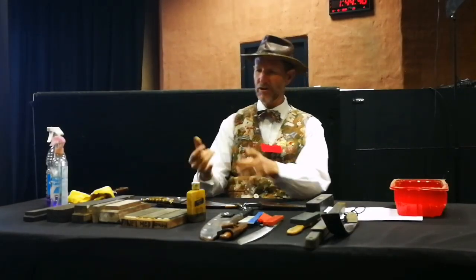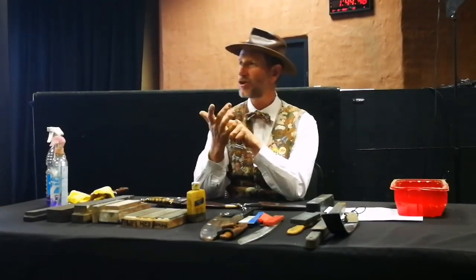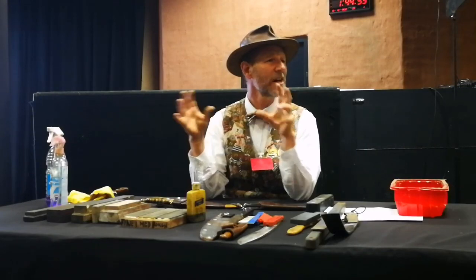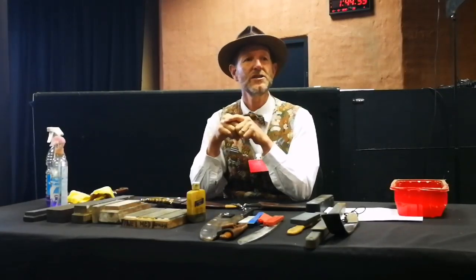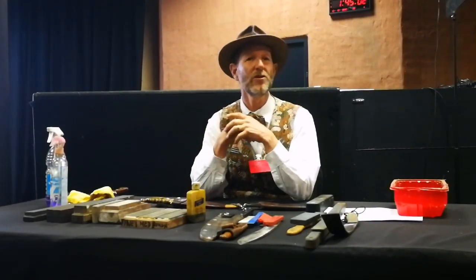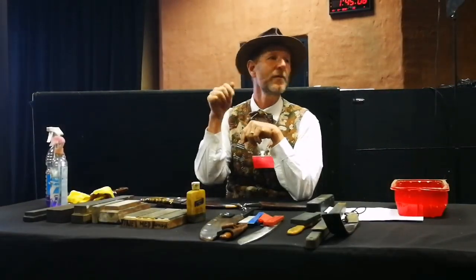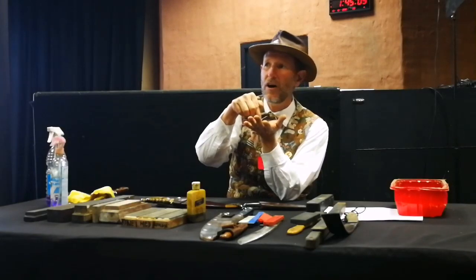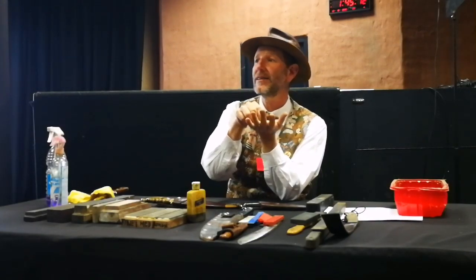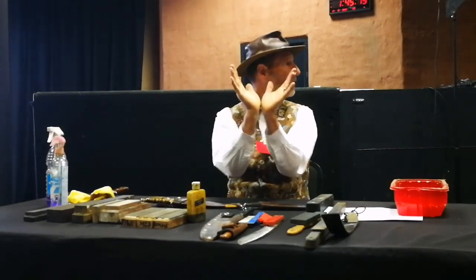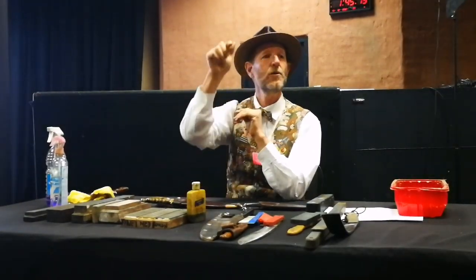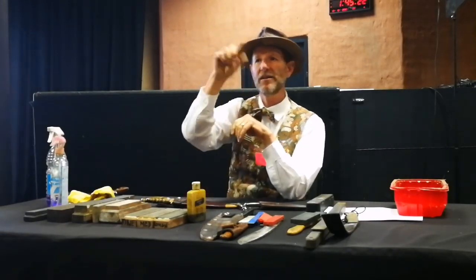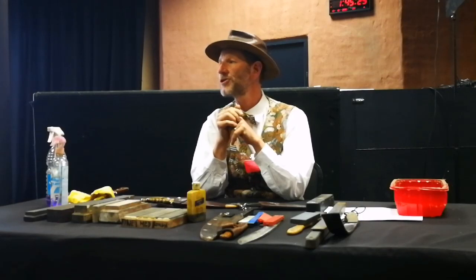You do get other scales. You get obviously Rockwell A and B. You get things like Brinell, Vickers, Charpy. They're all different ways of measuring hardness, impact resistance and toughness and things like that. Some of them can only be done in a laboratory environment. But Rockwell is a very nice way of testing wear resistance or resistance to penetration, actually. Because the way they measure Rockwell is by bearing down on your knife blade with a diamond point. The point of the diamond's got a very specific angle. I don't know what it is. But they will put a load behind that diamond, and that gauge will measure the depth of penetration.